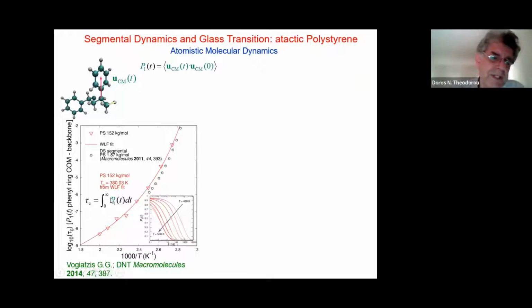Now, if one integrates this P1 of t, one has a correlation time, and it is very customary to plot the logarithm of this correlation time as a function of inverse temperature. As you can see, this plot is nonlinear. In other words, the dynamics is non-Arrhenius as regards its temperature dependence. If you go to lower and lower temperatures, the correlation times become disproportionately high, and that is associated with hierarchically constrained dynamics as one sees in glass-forming systems.